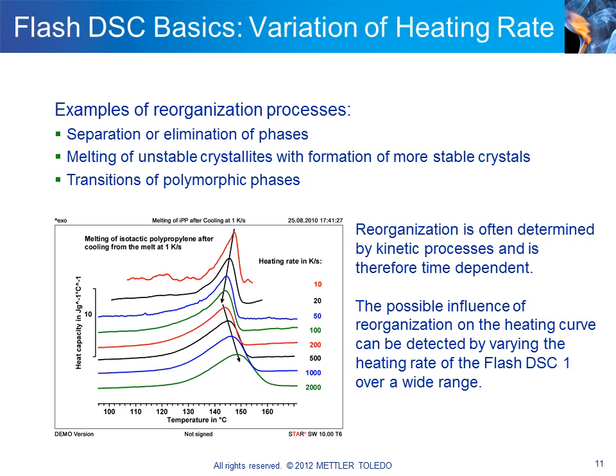The measurement curves in the inserted diagram show the reorganization of isotactic polypropylene on heating as an example. Before each measurement, the sample was cooled at 1 degree per second from the melt. The heating runs were then performed at heating rates between 10 and 2000 degrees per second.